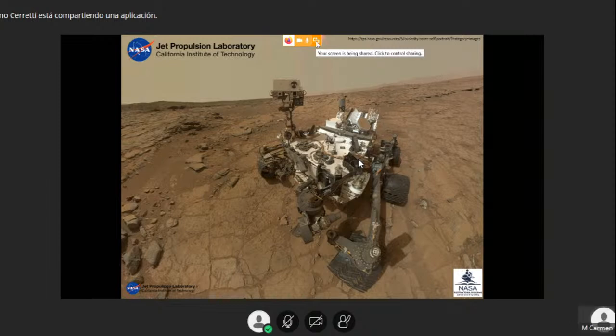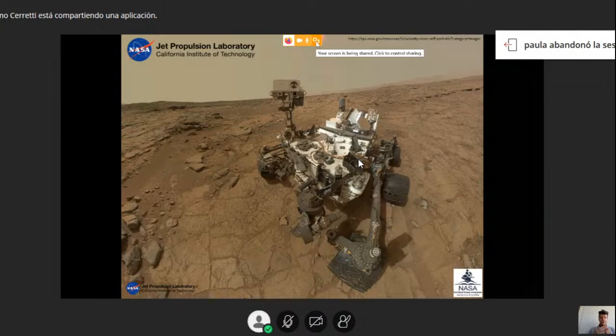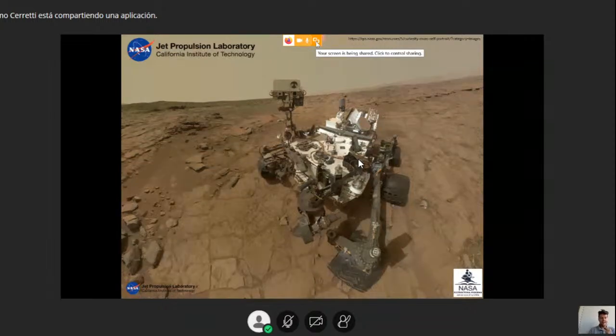Okay, so I'm probably going to reply in English because for some terminology, I think it might be easier or at least faster. Yeah, don't worry. For the MMRTG, the generators Curiosity carries, the temperature on the hot side is 530 C, and the cold side is 200 C. There has been a proposition for implementing new materials inside this generator to bring the efficiency from 6 to 8%, and the power output at the beginning of life from 110-120 to 145. This generator has a different material system. They're called skutterudites, and they have a hot side temperature of about 600 Celsius and 200 on the cold side.